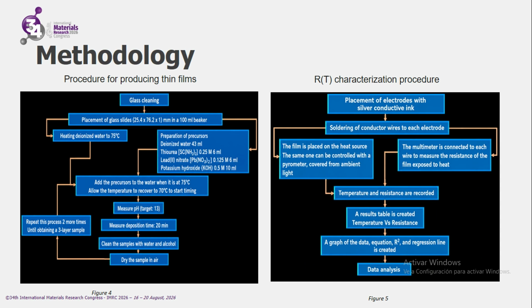Deposition time, 20 minutes. Clean the sample with water and alcohol. Dry the sample in air. Repeat this process two more times until obtaining a three-layer sample.